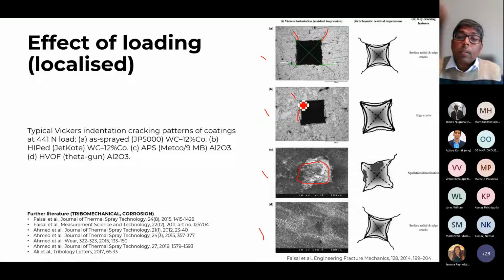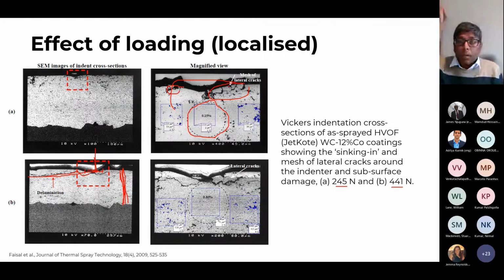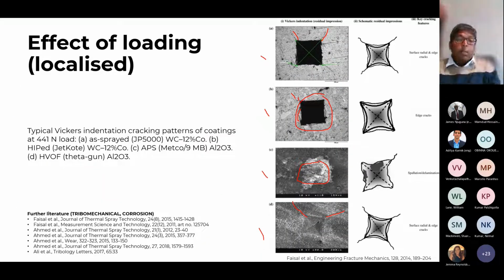So in this case, you can see there are no cracks. So this is the desirable one, where the crack stays localized. But here you can see the crack has gone very far off from the impression. So that is undesirable. But again, when you do the cross section of the indent, you can see subsurface, the lateral crack has gone very far off, even though on the surface it is very localized.